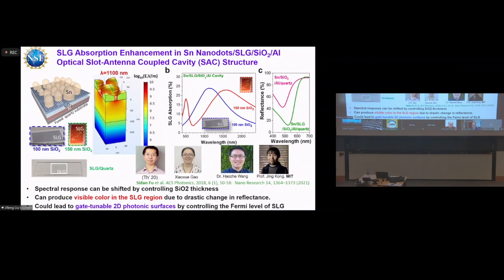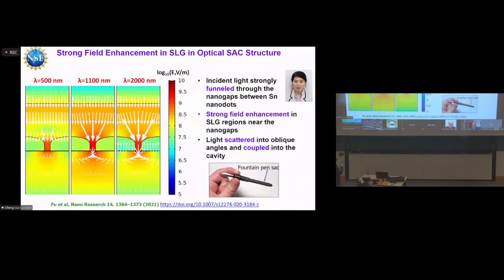So the graphene on silica is almost transparent, absorbs about 1.5% of incident light. But once you put on the dots, depending on the thickness of the silicon oxide layer, this is 100 nanometer thick, this is 150 nanometer thick, you can see not only the intensity contrast of the light, but also the color contrast. That's essentially due to this funneling of the light through these nano gaps into the cavity, and strongly interacting with a very thin layer of graphene right underneath these nano dots.